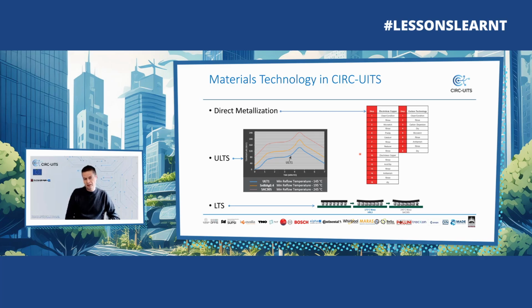So after drilling through holes in the PCB, you need to connect the various copper layers. And the incumbent technology there is electroless copper. Now, electroless copper is a very long process, which means it has various baths. It contains formaldehyde, EDTA, and cyanide, which are quite hazardous materials, as well as palladium, which is a very expensive element. So we have a technology based on carbon, which is called direct metallization. And it uses no hazardous materials. It uses carbon to make the holes conductive, so you can plate copper through the holes, making it conductive again. So it eliminates the use of the aforementioned hazardous materials.